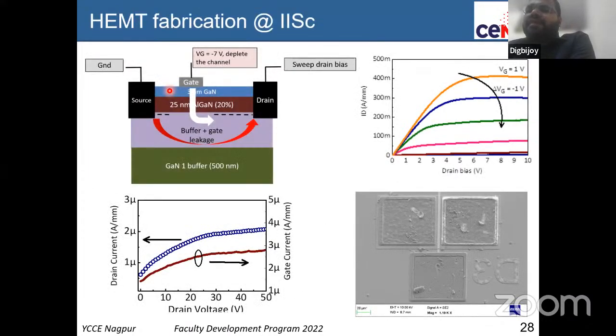So these are some of the devices that we had made at IISc some years back. This is a scanning electron microscope image of a device, a gallium nitride transistor. This is source, this is drain, and this is gate. There's a gate finger here. It's a small area device. The gate finger is probably a tenth of a millimeter. This is the periphery here, and it can carry a current of a few hundred milliamps per mm. So that's low current only. And this is the leakage that shows, it's up to 50 volts. We have much higher breakdown voltages, of course. You can block certain voltages.